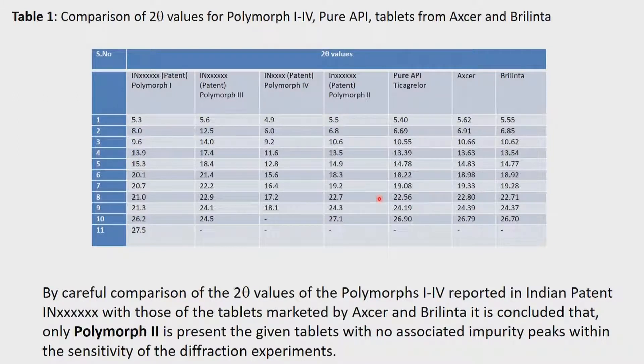The word of caution is that we should not take two samples, overlap them, and say we have a new compound or a new polymorph. The conclusion should be drawn by doing a profile refinement, and if structure data is available, Rietveld refinement — and of course, going to single crystals if possible will let you argue definitively that it is a new polymorph. What I have tried to do in powder diffraction in the last hour or so is essentially to give you the basics: the indexing procedure, the nature of the profile, profile fitting, pattern decomposition, profile refinement, and Rietveld refinement if structure is known.